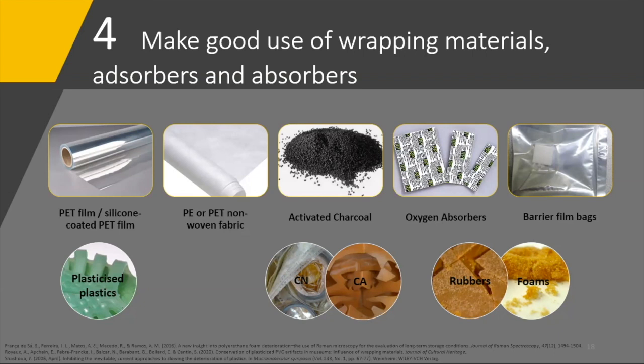However, in the case of plasticized plastics, as well as all plastics which tend to get tacky over aging, polyethylene should never be used because it promotes the migration of the plasticizer and the adherence of the wrapping material to the substrate. Then, for cellulose nitrate and cellulose acetate, adsorbents such as activated charcoal can be used, as these plastics tend to release acidic and other harmful compounds to the environment. And finally, rubbers and foams, as they are highly susceptible to oxidation, the use of oxygen absorbers in barrier film bags is highly recommended to slow down degradation processes.